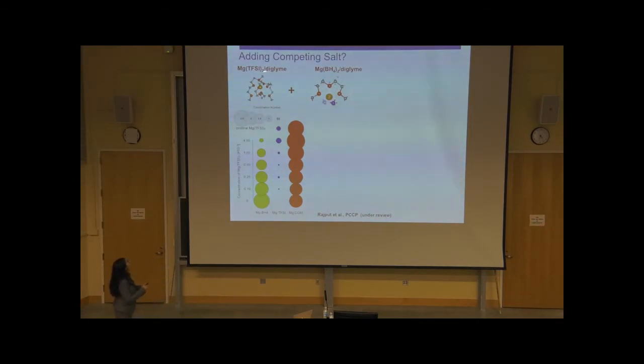Another thing we tried is adding two competing salts. So you can add magnesium TFSI diglyme to magnesium borohydride diglyme, and you let TFSI and borohydride compete with each other. And by doing that, we can significantly decrease the coordination number of magnesium borohydride as we increase the concentration of magnesium TFSI. There's a slight increase in the coordination number of magnesium TFSI, but it's not much because TFSI is a weakly coordinating anion. And in this fight between TFSI and borohydride to interact with magnesium, it's actually the solvent who wins, and the coordination number of magnesium solvent increases significantly.